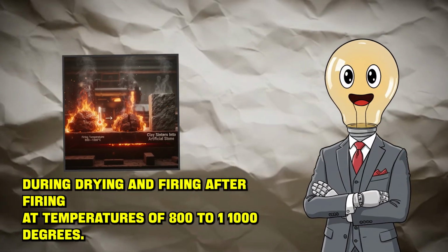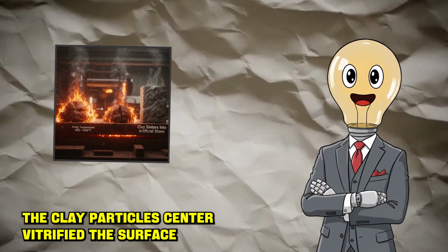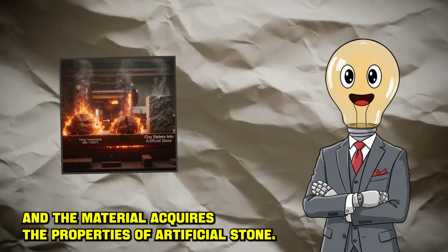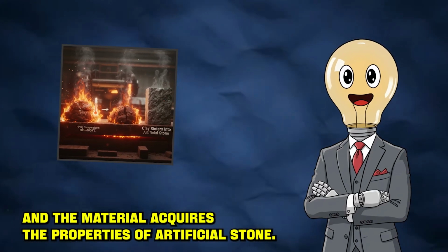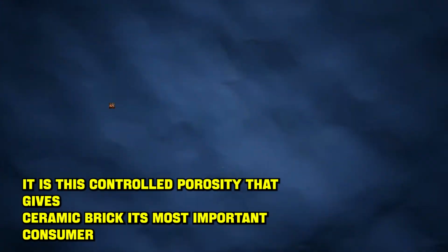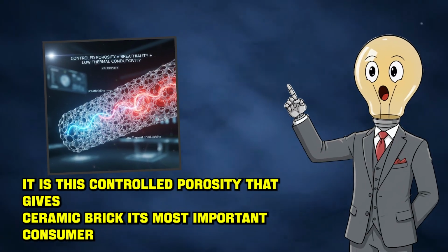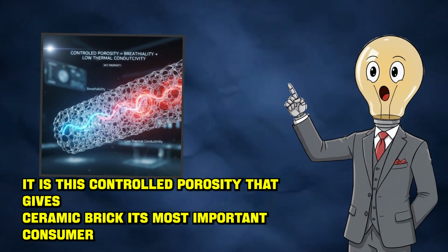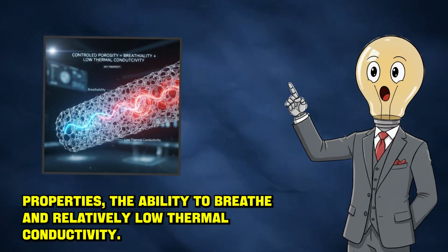After firing at temperatures of 800 to 1000 degrees Celsius, the clay particles sinter, vitrifying the surface, and the material acquires the properties of artificial stone, strong yet porous. It is this controlled porosity that gives ceramic brick its most important consumer properties, the ability to breathe and relatively